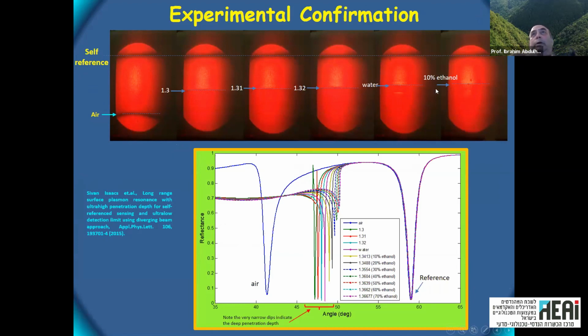So you need much better beam quality in order to see, right? Because it becomes narrow. But this goes back to the original requirements. When you have a very high figure of merit, like a very narrow resonance, you need a better signal to noise ratio, right? To be able to resolve it. So here we can see that we can resolve it still till ethanol, which is quite a good dynamic range.